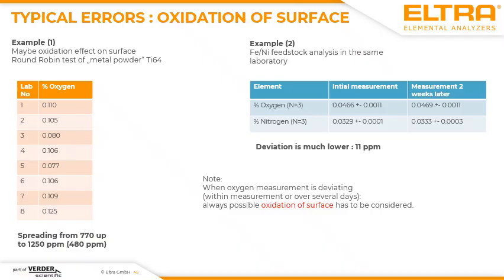And this could be caused by, I would say, different status of the surface, which means when you measure a sample today and send it to other customers or to other labs, please be aware that in this time the surface maybe could be oxidized. This was measured for titanium-based samples.